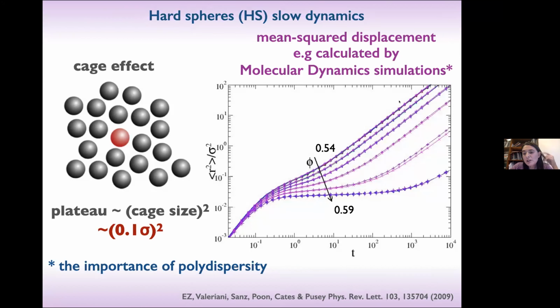And you see that each of these curves is for a different polydispersity, the ones where the system did not crystallize, and it basically tells you that there is no crucial dependence on polydispersity. So the MSDs that you measure are basically invariant. The important point is that you really have to include polydispersity, otherwise your system will crystallize and you will not be able to explore so many decades of relaxation.